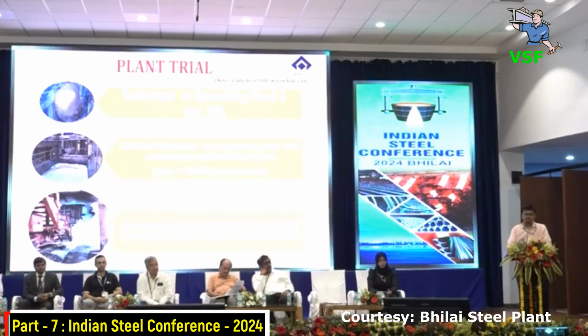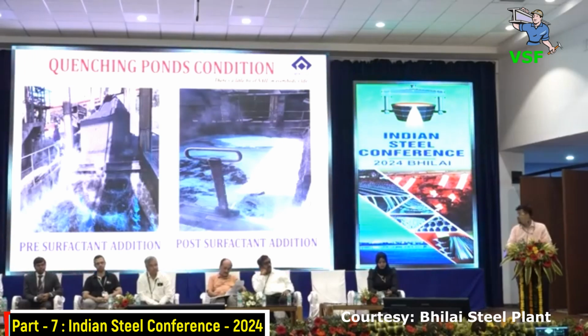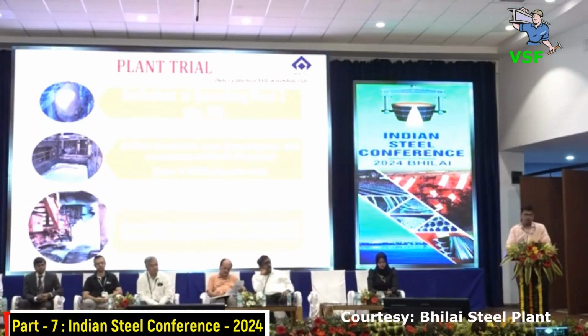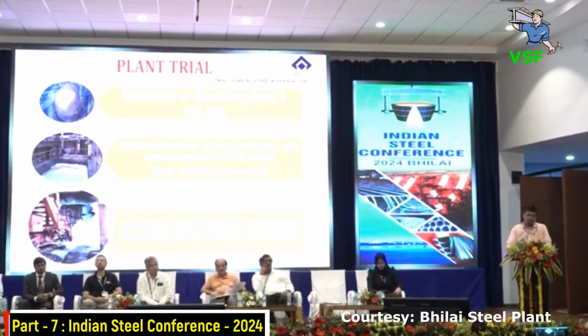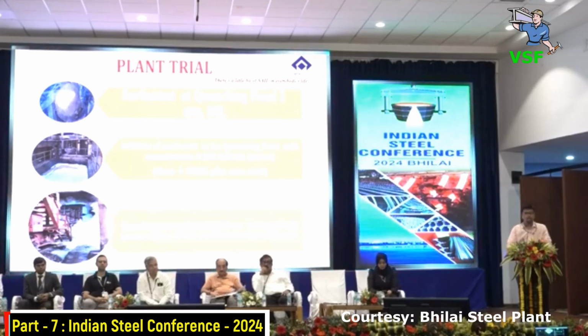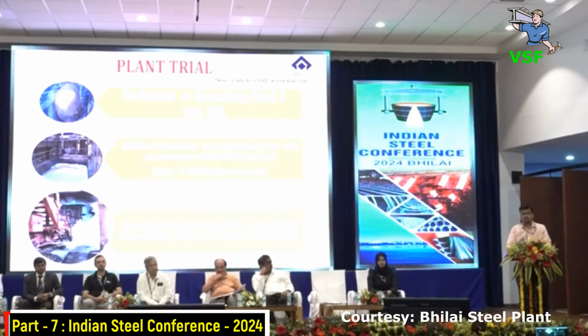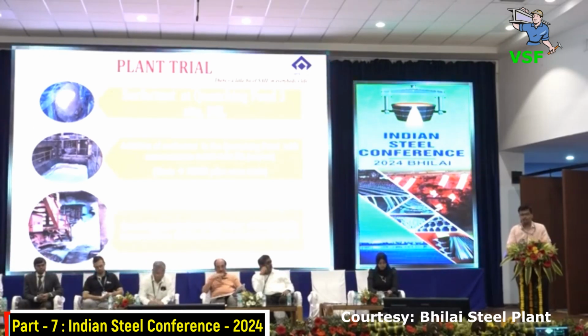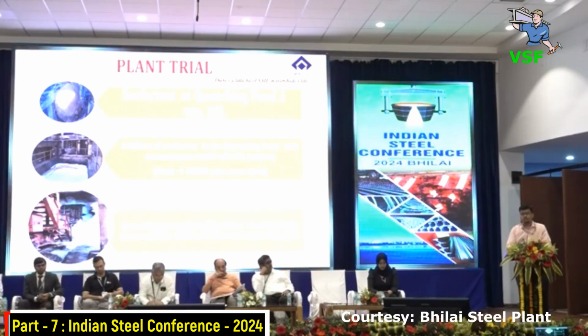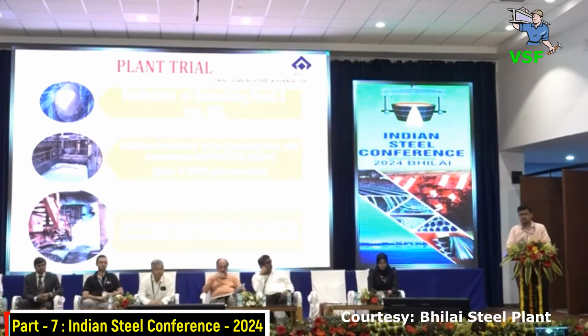Initially, RDCIS conducted some pilot oven trials with varying concentrations of surfactants. With all those trials, we concluded to some percentages, and from these percentages, we conducted plant trial at Bokaro Steel Plant, and quenching point 3 was selected as it catered to coke oven battery 7 and 8. So the surfactant was added in the concentration of 0.009 to 0.013%, and this percentage was on the basis of the RDCIS pilot oven trials.